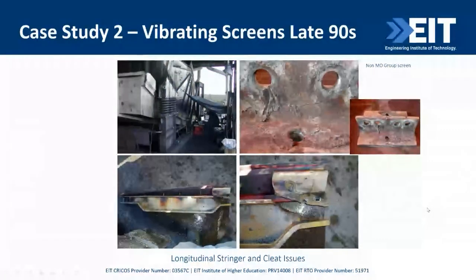This is an unfortunate case of a longitudinal stringer where they tried to reduce the height of the top of the stringer above the cross beams and the cleats by tapering the ends here to bolt into the cleats. It's a bridge too far. The weld here, you've gone from parent metal of the channel to a weld, and even though the weld was done well and ground and stress relieved, etc., a bridge too far, just cracking all the way through.